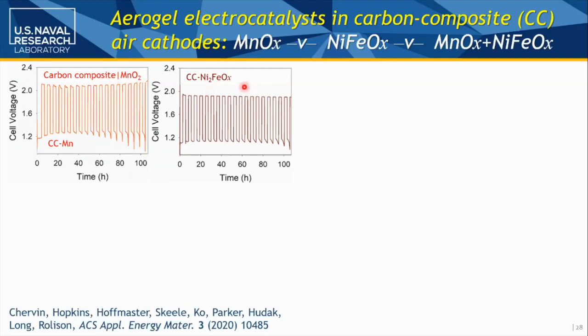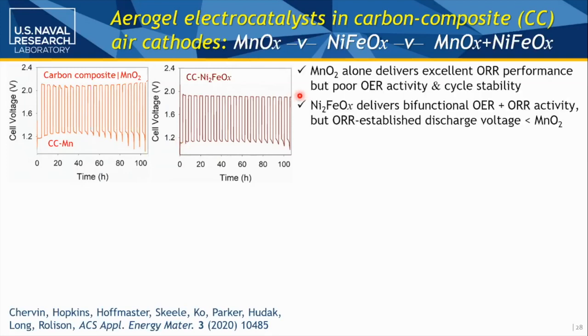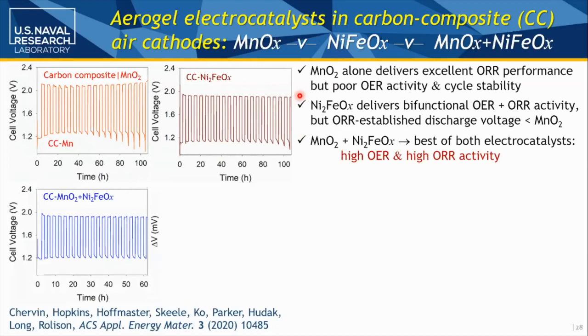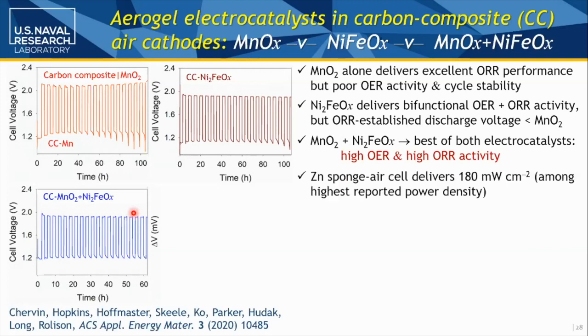Whereas if you're just looking at the nickel ferrite, it's got some bifunctionality. You're perhaps not getting quite as high an initial discharge cell voltage as you'd like, but you keep the charge well under 2 volts. So put the 2 powders together into our carbon composite and you get the best of both worlds. You buy back a better discharge cell voltage. You're keeping it below 2 volts to charge. And we're getting some of the highest power density out of a powder composite.